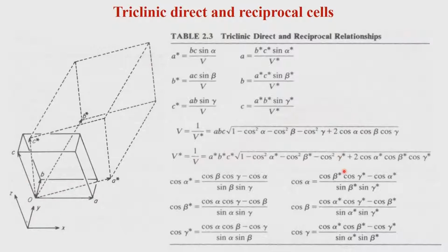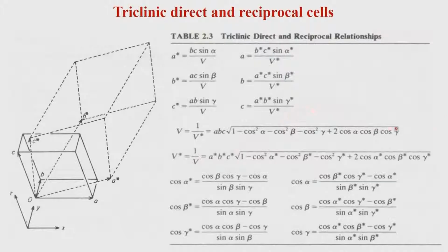And these involve so much trigonometry. The orientation angles come in, and those go as products of cosine alpha, cosine beta, cosine gamma, and therefore, you will get these expressions. You see the volume now, which is simply again written as A dot B cross C in vector notation, will be equal to ABC times the square root of this quantity, which involves the cosine square functions and also the cosine functions associated with alpha, beta, gamma.